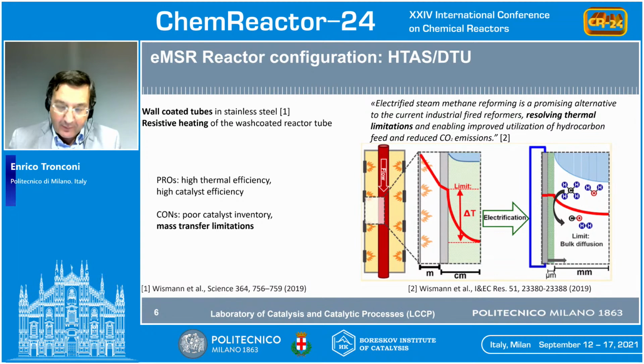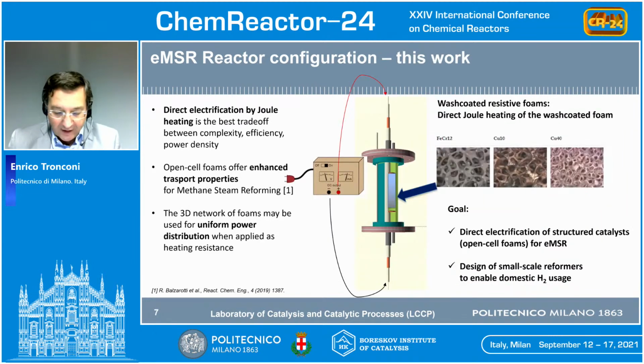On the other hand, the performance of a reformer with wall-coated tubes is eventually controlled by external diffusion, gas-solid mass transfer, which calls for the adoption of tubes with small diameters, leading eventually to the development of a reactor solution which is based on either honeycomb monoliths or microchannel technologies. In Milano, we are working on an alternative solution for the electrification of steam reformers, which is based on the direct Joule heating of open cell foams, also known as sponges, so cellular materials.